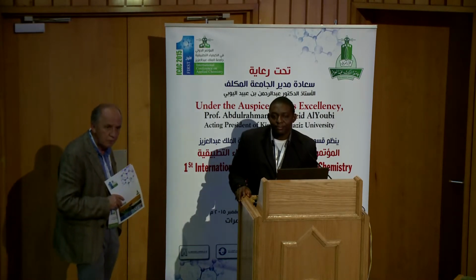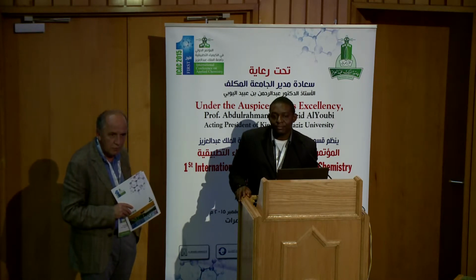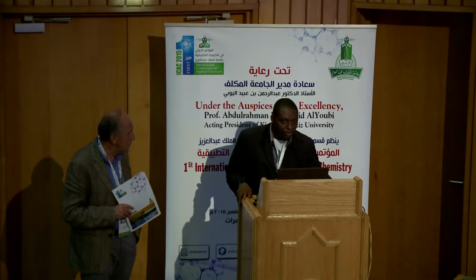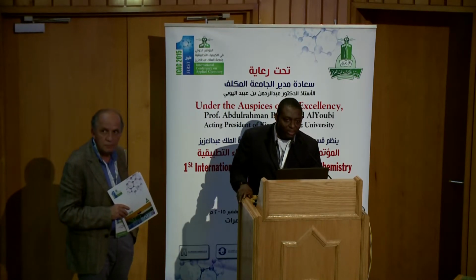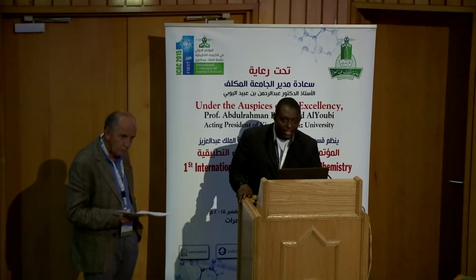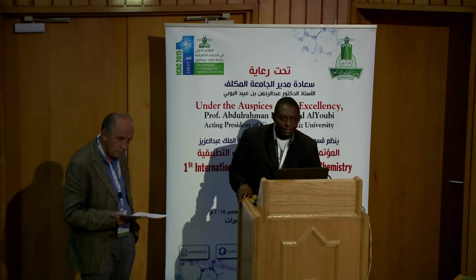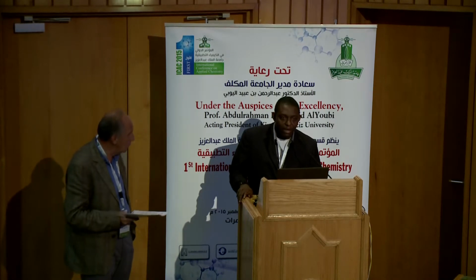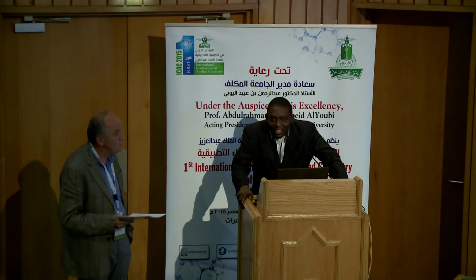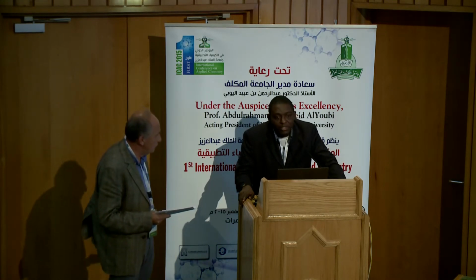I would like you to characterize your structure by elemental analysis, FTIR, and NMR, but you didn't do mass spectra. Yes, usually mass spectra for polymers is very difficult because these are large molecules. We are talking about almost 300,000 molecular weights. Yes, but you can do with mass spectra to get the exact molecular weight. I think for associating polymers, the best is MW. MW is the absolute molecular weight you can get, the best. Then followed by MV, which is molecular viscosity. If it is possible, you can do MN, for which you need GPC. But for associating polymers, mass spec is not the best choice.